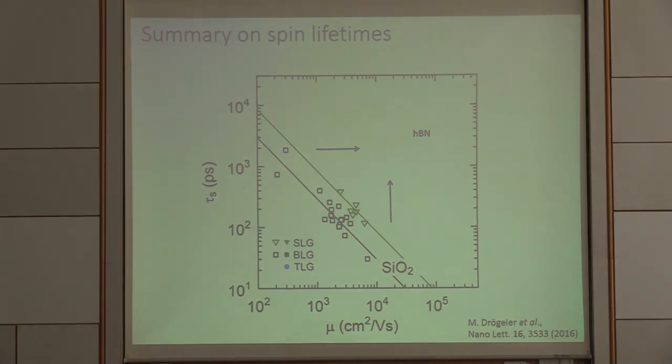I can again put this into this plot here. So that's what I showed you before. And now we are actually here. So we see that we could still improve a bit. So 100,000 at room temperature. All that I show you here is room temperature. We will never go beyond this barrier here. Because 100,000 at room temperature, at one point we are limited by phonons. It's very hard to fight against them. But in this direction, we don't know how far we can go.